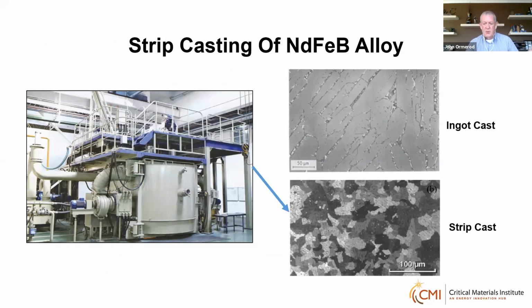Now, the major problem with producing neodymium iron boron alloy is that the Nd2Fe14B intermetallic forms from the melt by a peritectic reaction. Now, at normal cooling rates, i.e. ingot casting, that reaction does not go to completion. You end up with large grains of 2-14-1, and then a boron-rich phase, some neodymium-rich phase, and a lot of alpha iron precipitates out. And the alpha iron is a real problem when it comes to crushing and milling the powder. And of course, if it gets through to the final sintered magnet, it really spoils the magnetic properties.